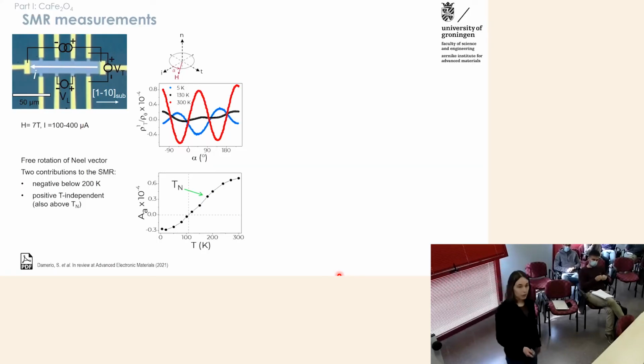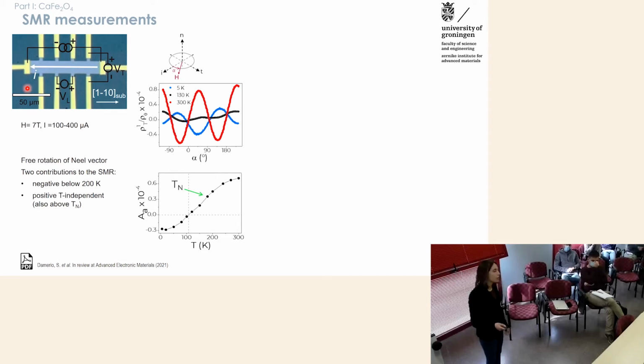So what we did to begin with was build larger Hall bars, which can cover different crystallographic domains on our films, and start to measure the spin Hall magnetoresistance in the plane of the film. Here what we see is that when we start at low temperature, 5K, we observe a modulation with the sine of 2 alpha. And this modulation has the periodicity of a classic negative SMR, so what you would expect